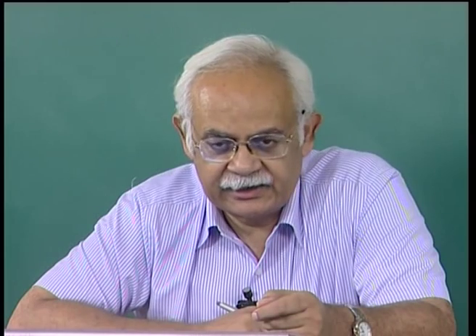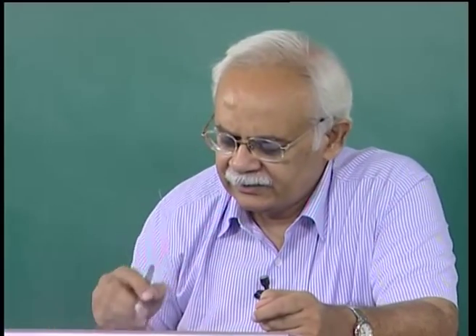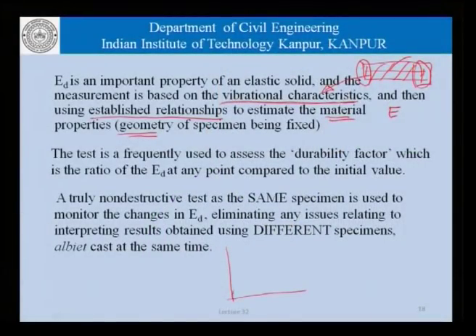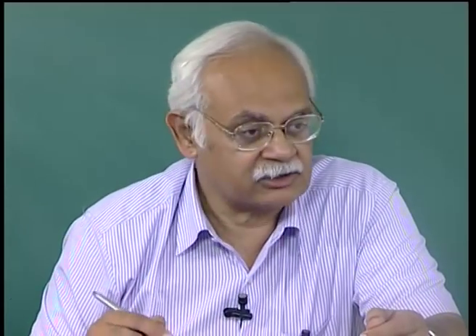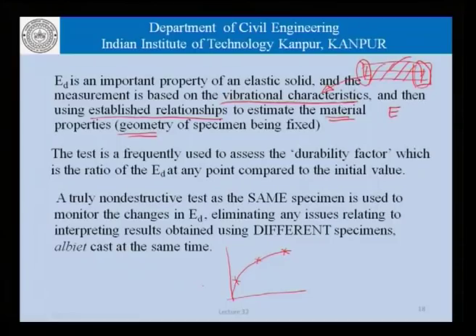If I were to explain that once again, we know that concrete develops strength over a period of time. We know that the strength of concrete is so much here, and so much here. How do we get this information? We get this information by testing cubes or cylinders which are cast at the same time, but tested here. Some other cylinders are tested here, some other cylinders are tested here. We assume that the concrete is the same, and therefore, whether we are using different specimens or the same specimen, it really does not matter.